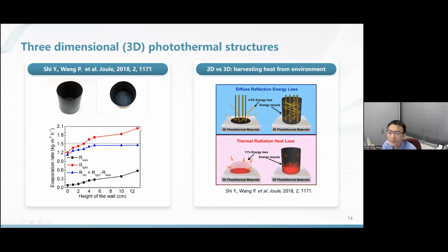What was the reason? Two reasons. They were listed on the right-hand side. The first reason is that such a design was able to convert solar energy to heat with very high energy efficiency, almost 100%. The second reason why such a system can break the ceiling is that with this design, as you can see from this top part, during water evaporation, the majority part of the evaporation surface has a temperature that is lower than the ambient air. Now, there is a favorable temperature gradient that drives energy to come from the air onto the material. So such a design has two energy sources, solar energy and ambient air. That explains why our system was able to break this 1.5 ceiling.